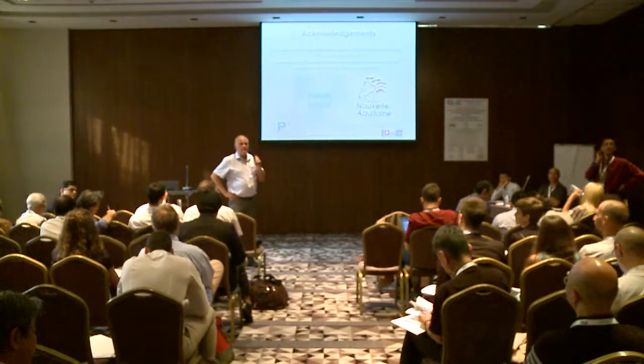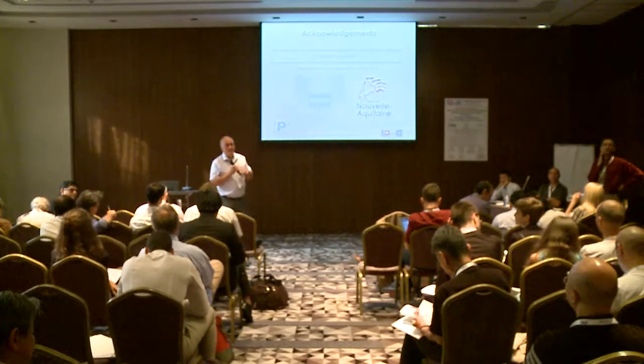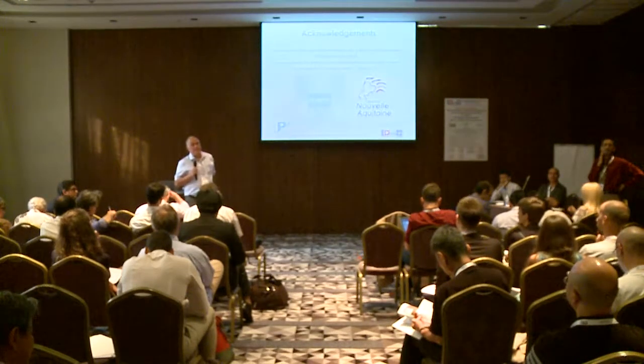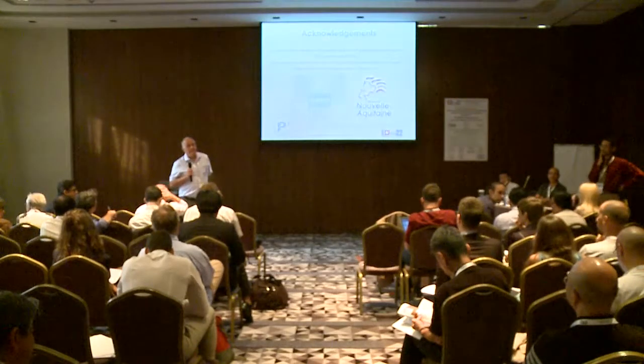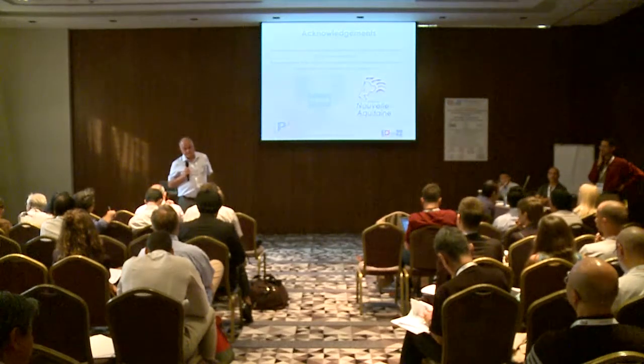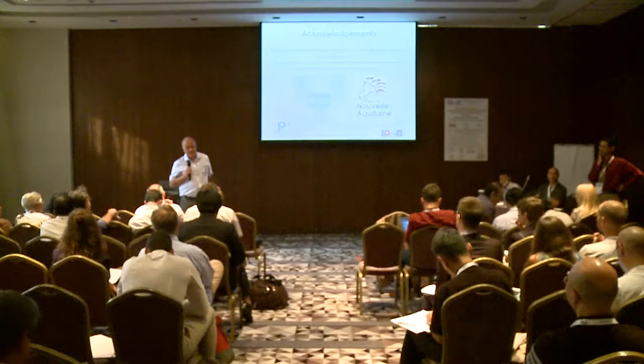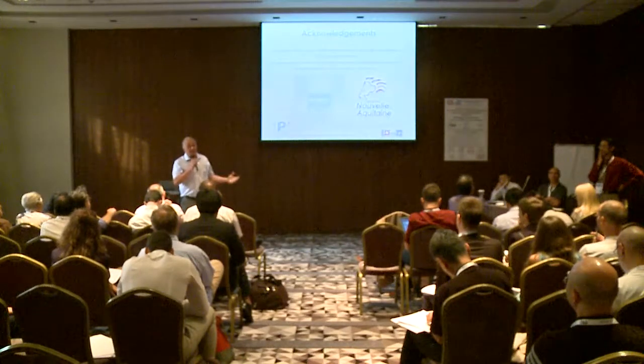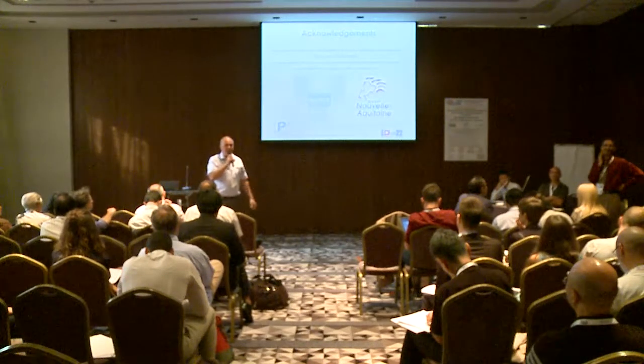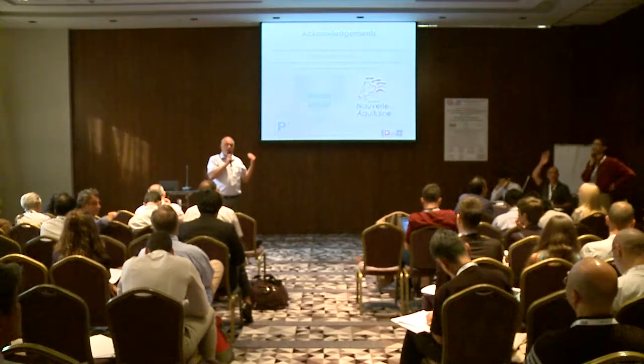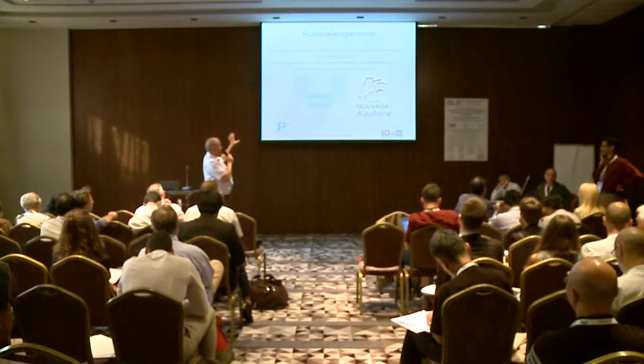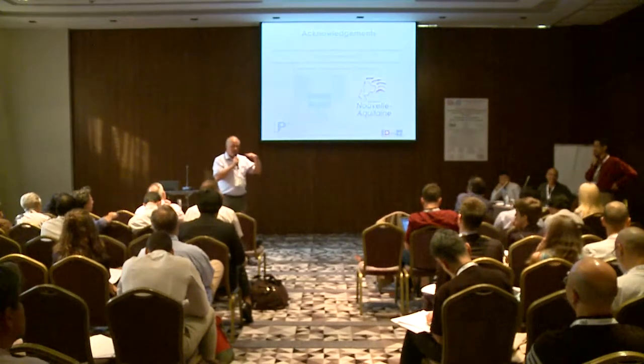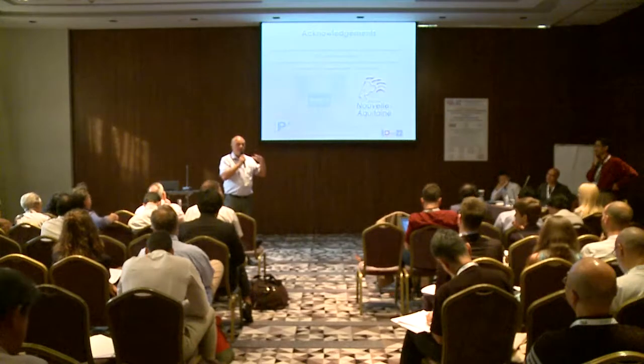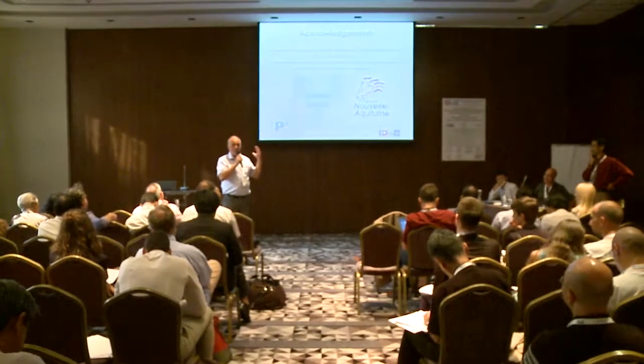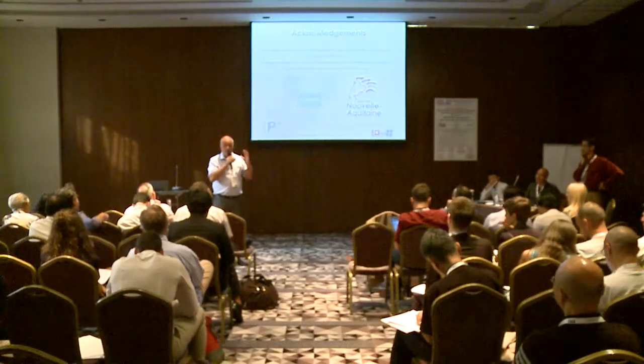That was my question. Does hydrogen pressure change mechanisms at all? When you compare a low pressure hydrogen fatigue or overload fracture with a 100 megapascal type pressure? That's a good question, but I have no definitive answer about this. But actually, maybe I was not clear during my presentation, but the point is that this intergranular fracture in the case of pure iron doesn't look brittle at all.